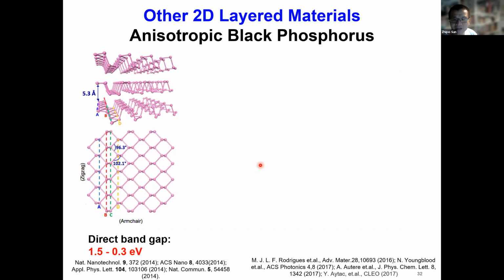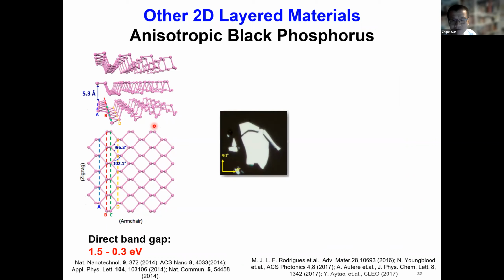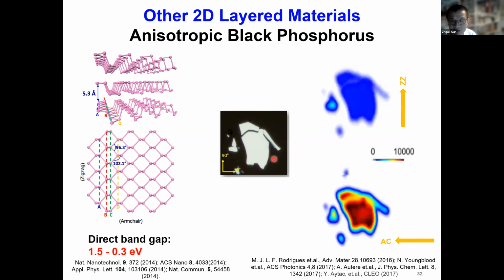We also worked with black phosphorus, which has a very strong anisotropic response. We checked the third harmonic generation of black phosphorus. For example, this is a flake we got from Northwestern University. And we found that when the input light polarization is along the armchair direction, we get a much, much stronger third harmonic generation. But when we change the light polarization along the zigzag direction, the third harmonic generation is much, much weaker.